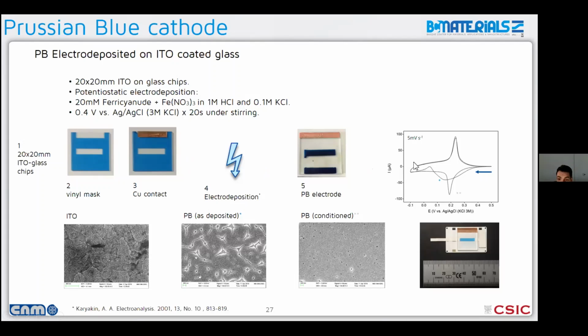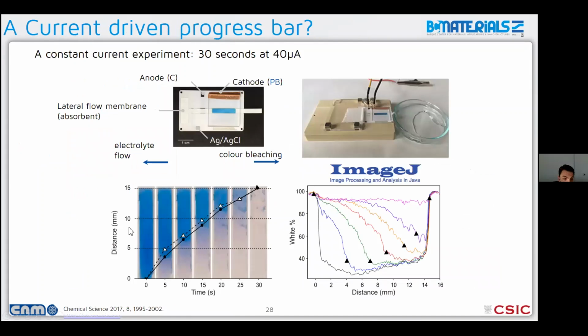And then we basically conditioned the material, because to get the best results, we had to do some electrochemical cycling in HCl, and you can see that the surface of the material improves a lot. It becomes a lot more homogeneous, and actually the response is very, very good. It's quite reversible. So then we started playing with this.